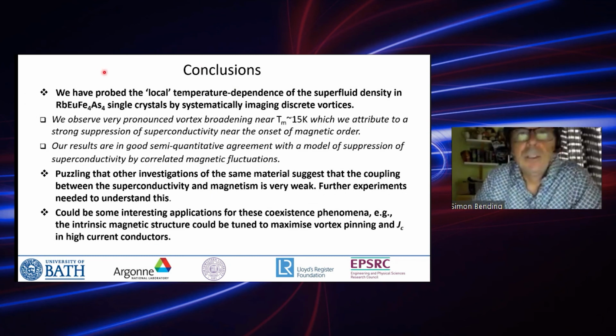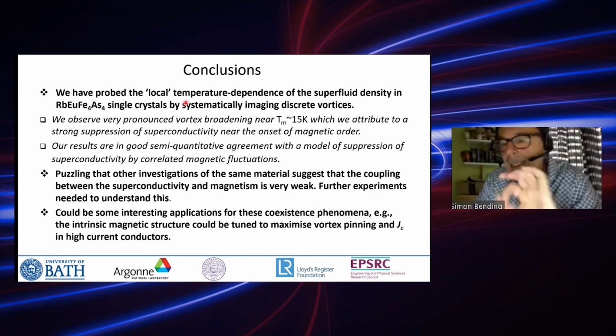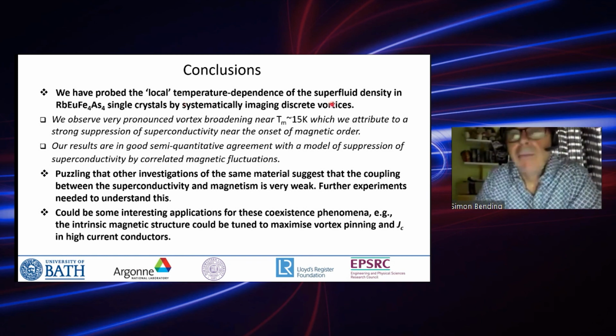So that brings me then to my conclusion slide. So we have probed the local temperature dependence of the superfluid density in rubidium europium iron arsenide single crystals by looking at discrete vortices and measuring the superfluid density by measuring the temperature dependence of essentially the profile of these vortices and fitting that to a model due to John Clem. We clearly see a very pronounced vortex broadening around the magnetic ordering temperature of 15 Kelvin, which we attribute to a pretty strong suppression of superconductivity or the superfluid density near the onset of magnetic order. And the results are really in good semi-quantitative agreement with a model due to Alex Koshelev of the suppression of superconductivity by correlated 2D magnetic fluctuations.